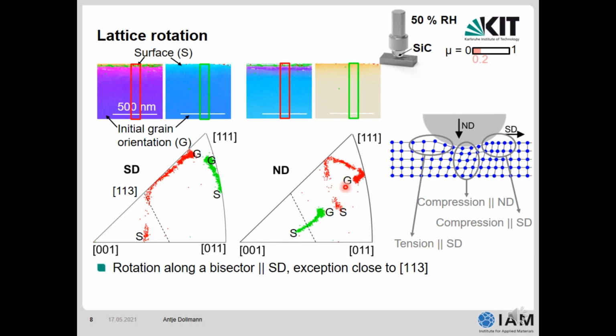And what is quite interesting here is that we see that the green grain rotates from the part of the IPF where the twins are favored under tension, to this part where twinning is favored under compression. And here in the surface near area, we have seen the twins. And this is why I think that the lattice rotation leads to the twinning and that the compression parallel to ND is responsible for the twin formation.